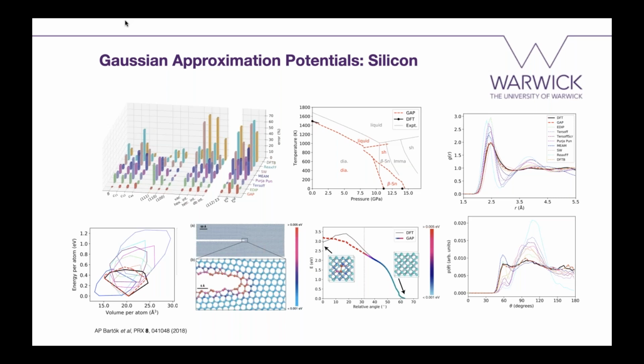And then going further and in a bit more detail, the next plot is a radial distribution function for liquid silicon, and then again DFT and GAP match quite well, and you can see that some of the more traditional interatomic potentials give quite unrealistic RDFs. And below that is the same for angles. That's the angle distribution function, and again GAP reproduces the DFT results quite well.